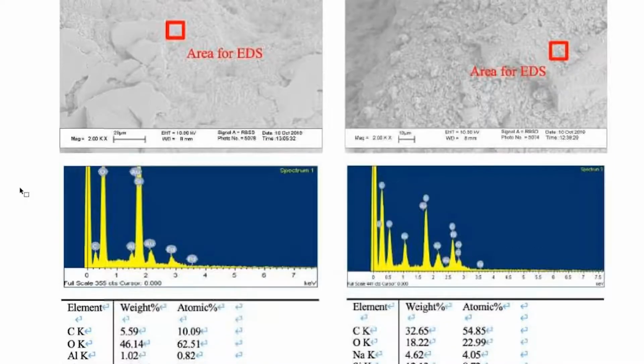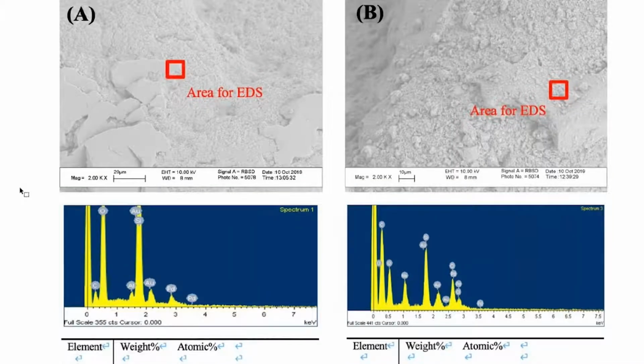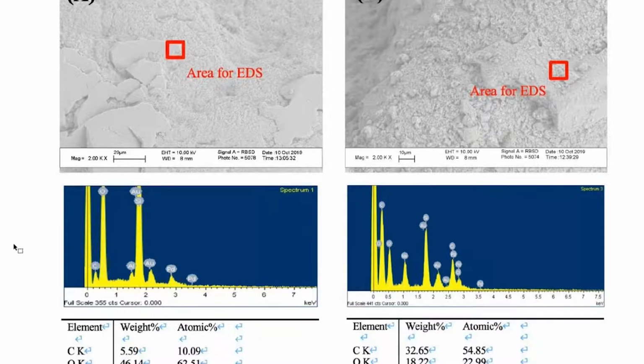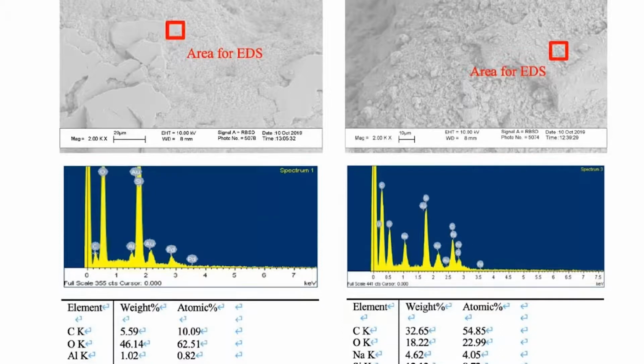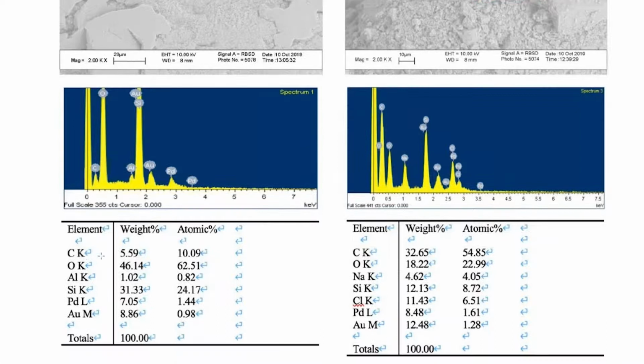So what we did was we ran EDS. So this is a way to look at the elemental composition, and you can see these scans down below. And of course, you get a lot of oxygen and different elements. But what I want to show you, this C is the carbon, and you see it jumps way up on the right-hand side. So we basically scan this little zone, and you'll see that these are a lot of our elements here, but the carbon goes way up, and that demonstrates that what's on that surface are the beads, the carbon beads.